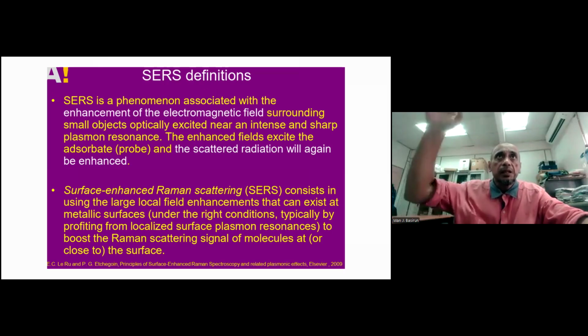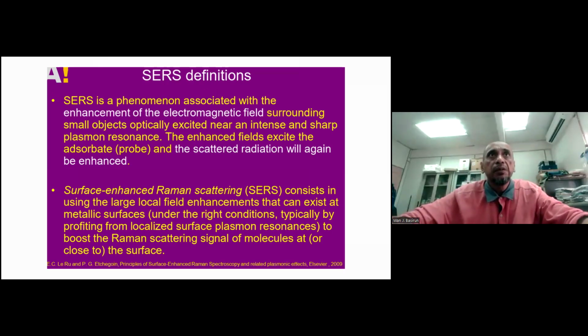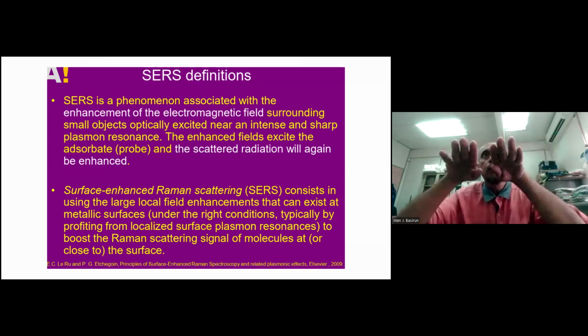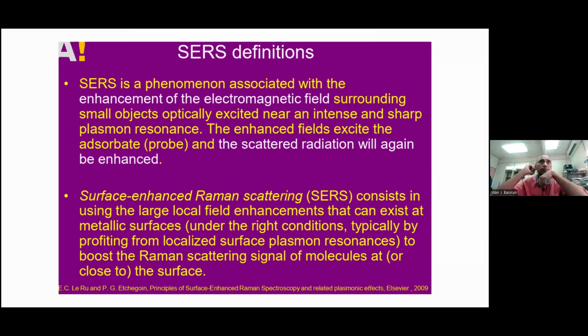Okay, so what is the difference between SERS and Raman? SERS is a phenomenon associated with the enhancement of the electromagnetic field surrounding a small object optically excited near an intense and sharp plasmon resonance. So this has to do with plasmon resonance. So what is a plasmon? A plasmon is a quasi wave which happens on the surface of the metal. And not all metals will give you plasmon resonance. We come to that later. SERS also uses a large local field enhancement that can exist on a metallic surface under the right conditions. So only certain metal surfaces will give you plasmonic resonance. When you have a plasmonic resonance, that contributes to the electromagnetic enhancement. So first of all, this is the condition of SERS.